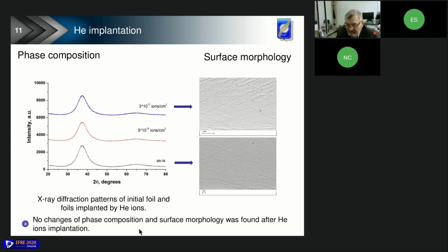At the first stage, the reaction of the initial foil structure to helium implantation was investigated. From this slide, you can see that no changes were found in the diffraction pattern of the foil before and after implantation up to this dose. A similar remark can be made on the surface morphology of the foil. Of course, the question of structural changes visibility is closely connected with the techniques used.